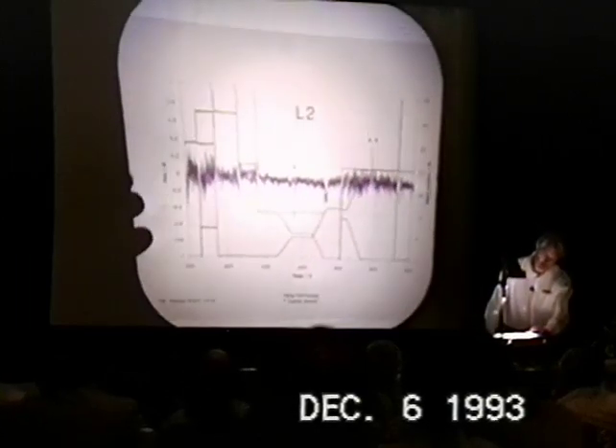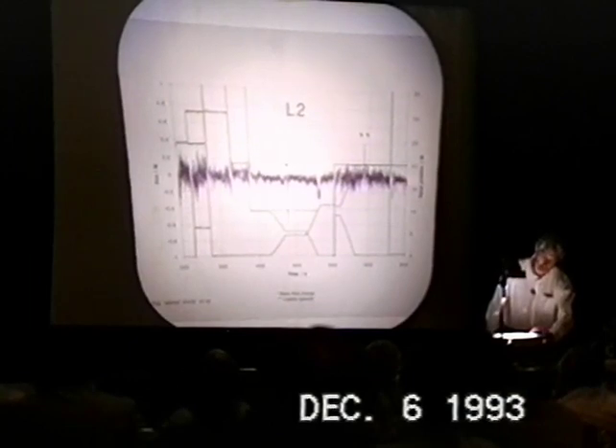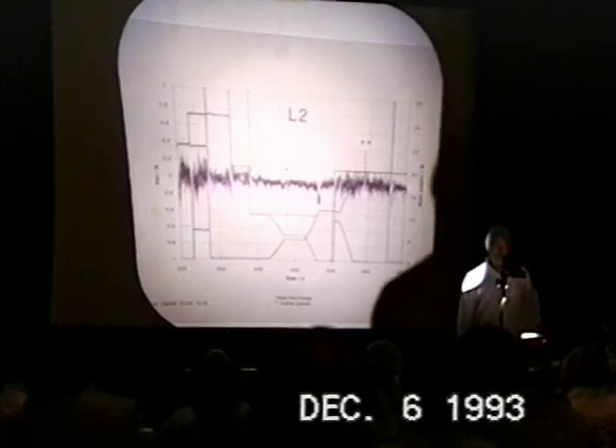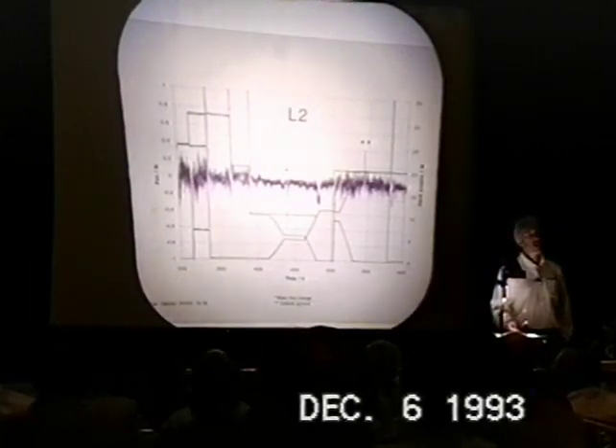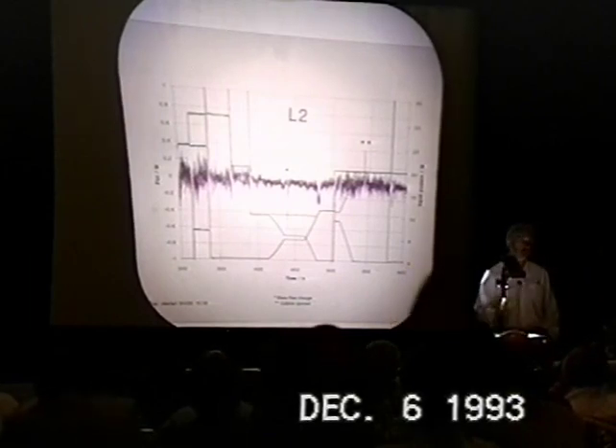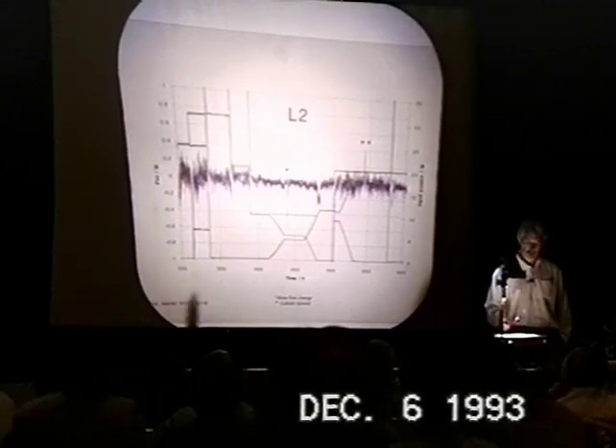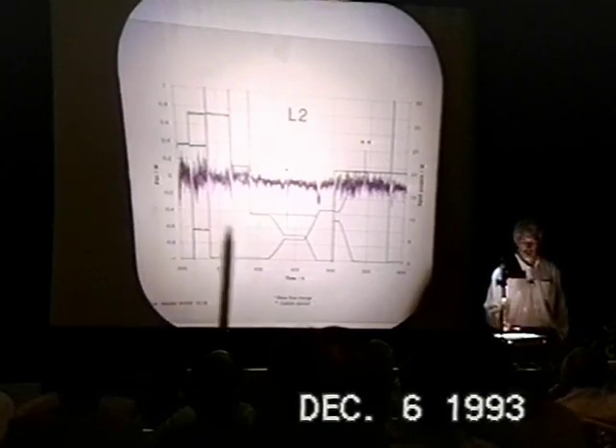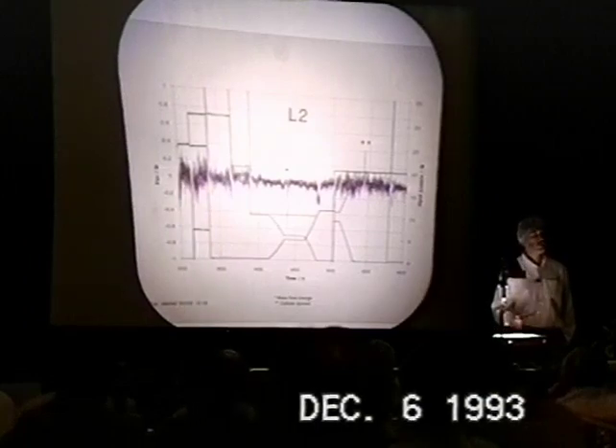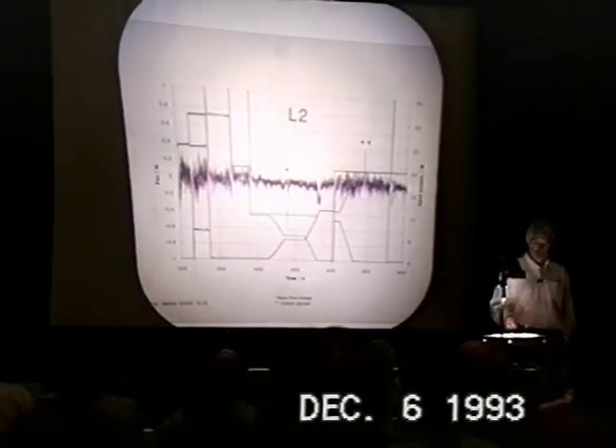This is a section of data from L2. Nothing succeeds as a blank for these experiments as well as a cathode which doesn't load. And we ran these 2 cells for very long times and were able to establish the stability and accuracy of the calorimeter for no other reason than we had not obtained sufficient loading in these particular cells to observe any excess heat, at least. So these are raw data, in fact, without the non-steady state correction, which reduces this apparent scatter markedly.